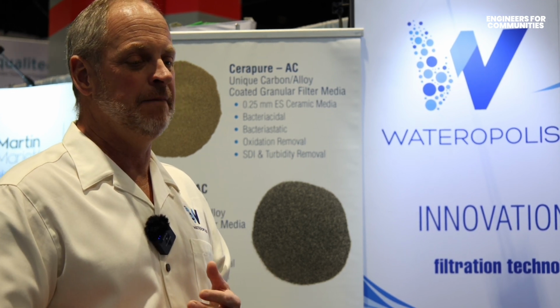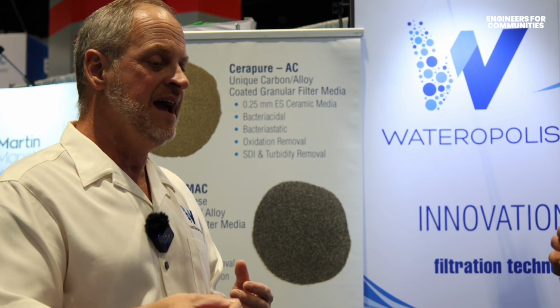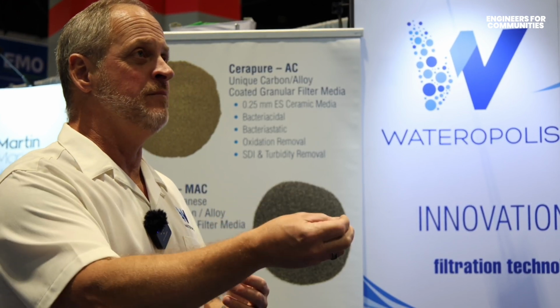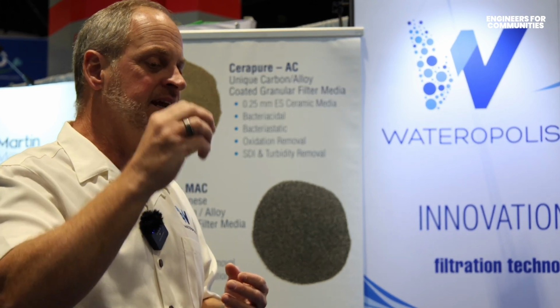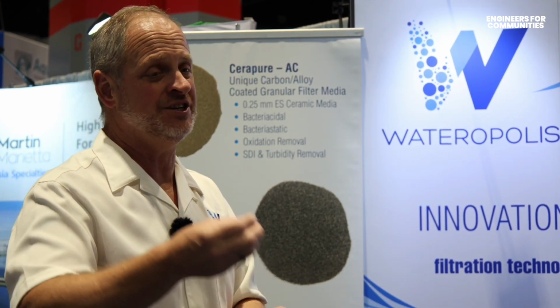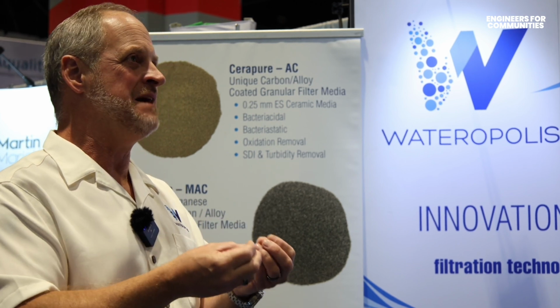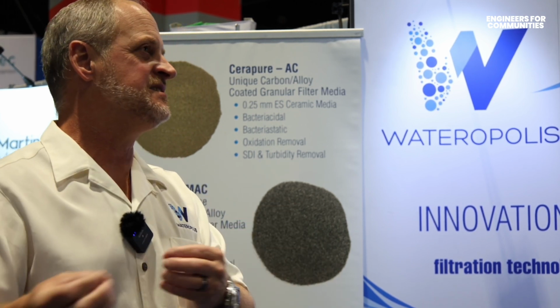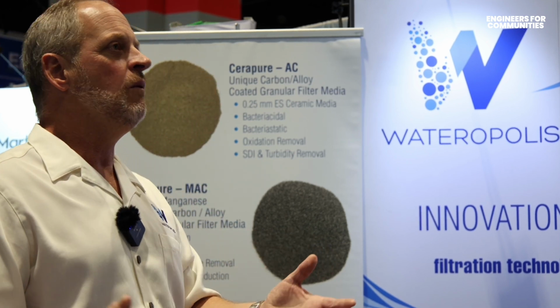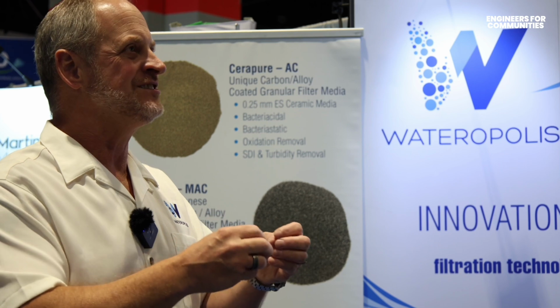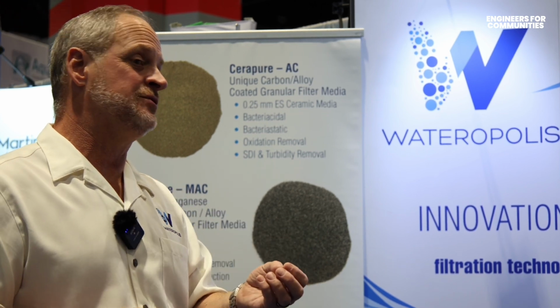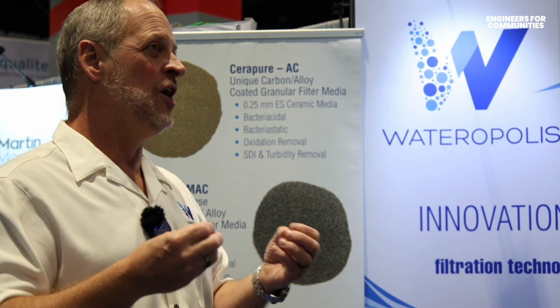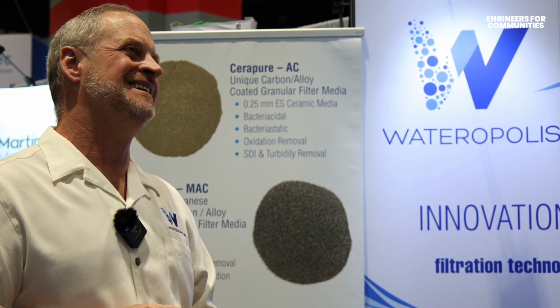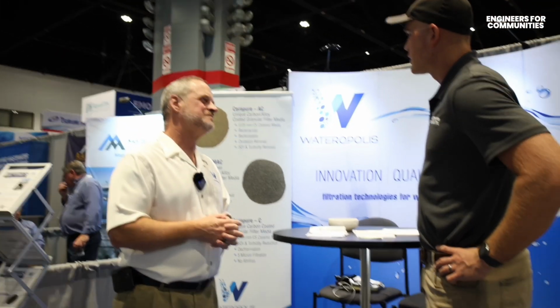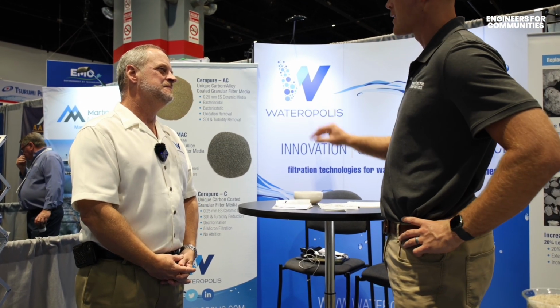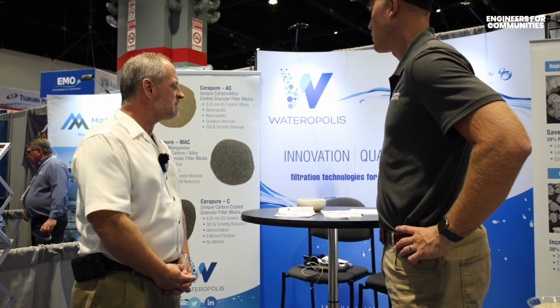I have clients that will take an inert ceramic like ours, and when they put it in they feed permanganate, and eventually the permanganate chemical creates that coating on the media. Eventually they can shut the permanganate off because they've basically put an MnO2 coating on the media. Then someday they replace the media, which they probably didn't need to do, and they go, why isn't my system taking out manganese anymore? Well, you've lost that coating. So sometimes we even go into filters and intentionally create that coating to help create a catalytic surface for taking manganese out. So interesting. So talk me through some of those other design elements when you're selecting your media that people should consider.